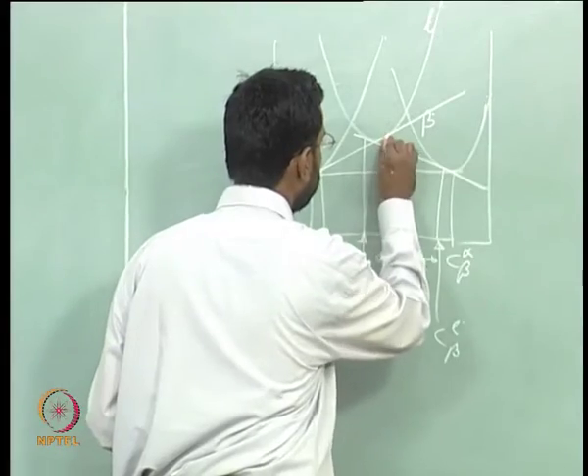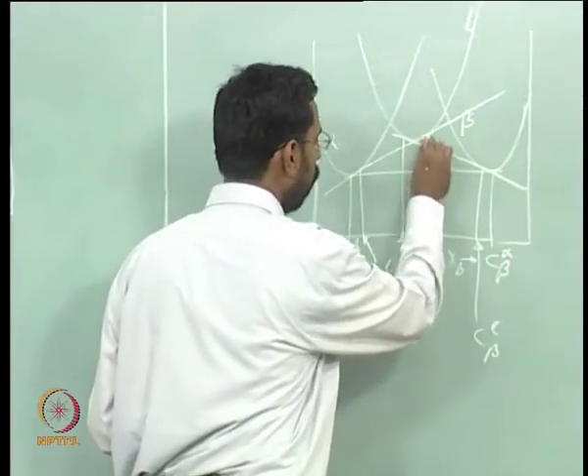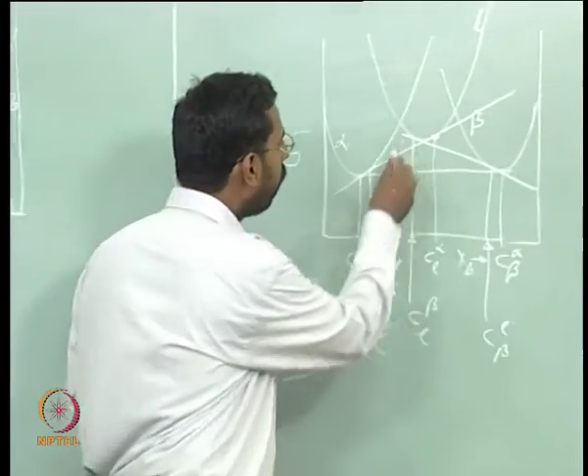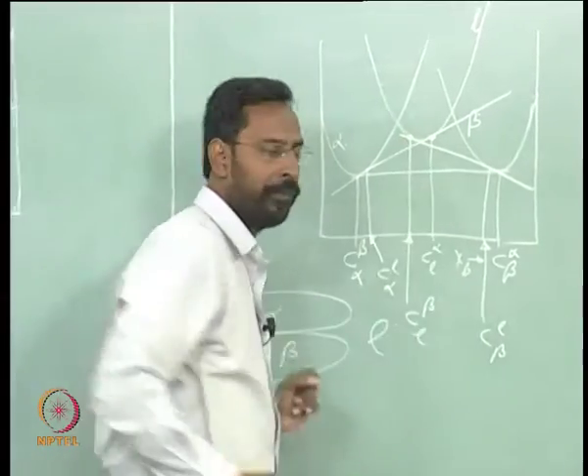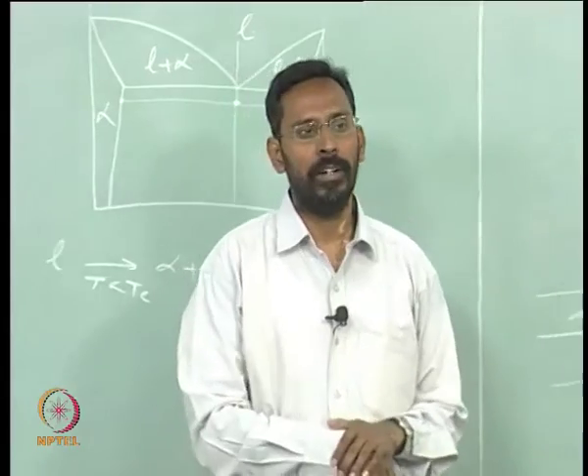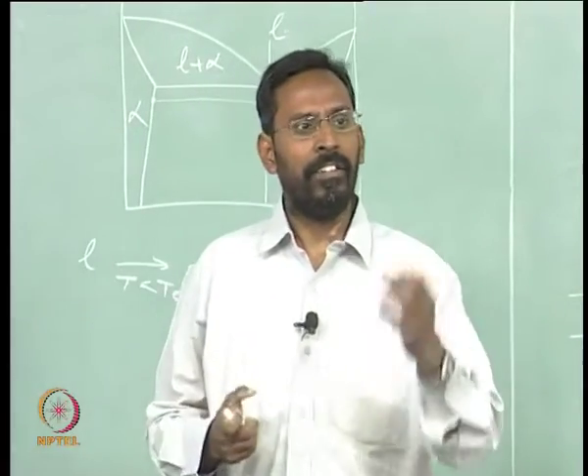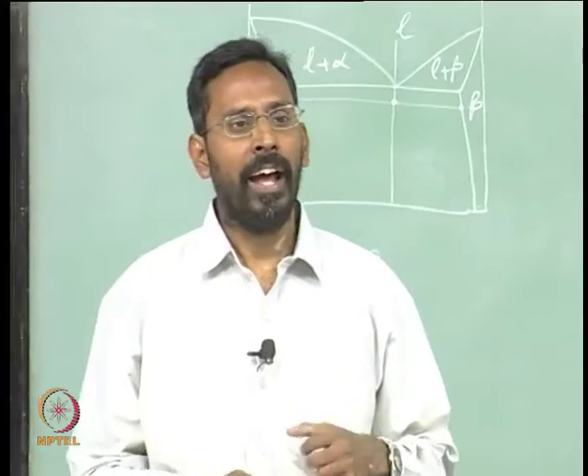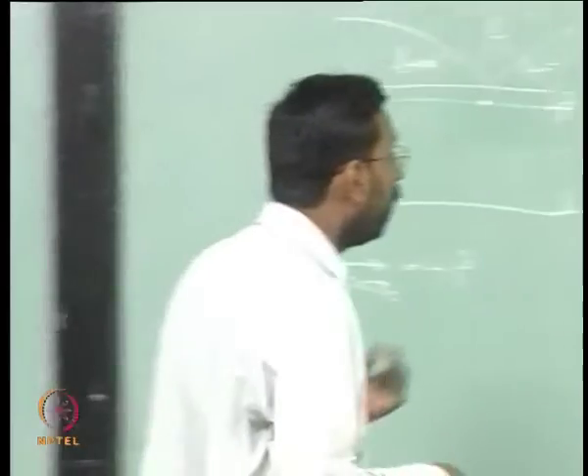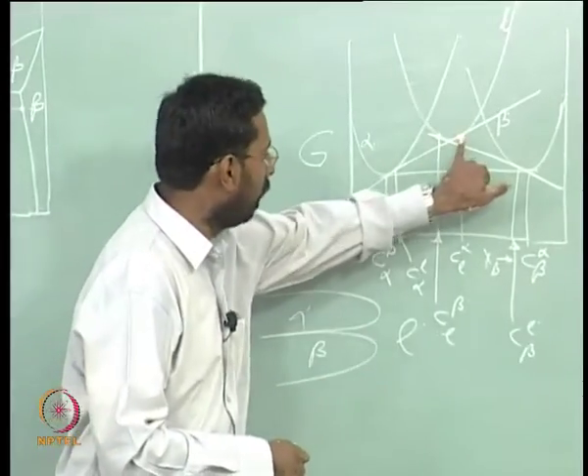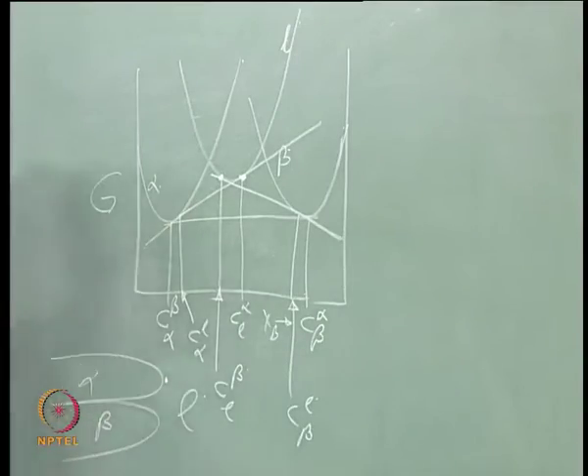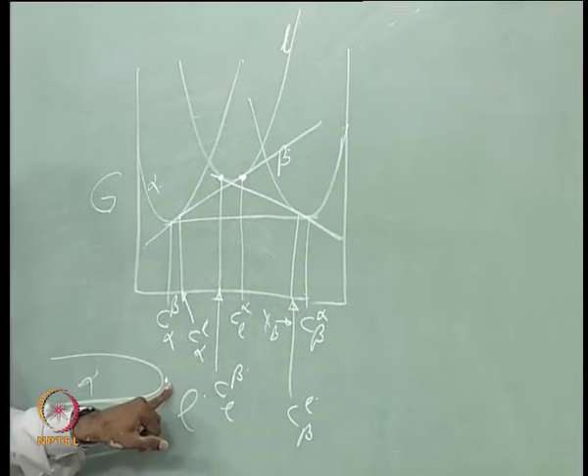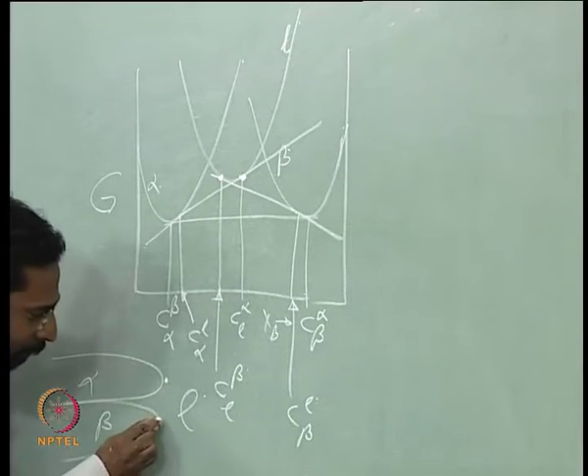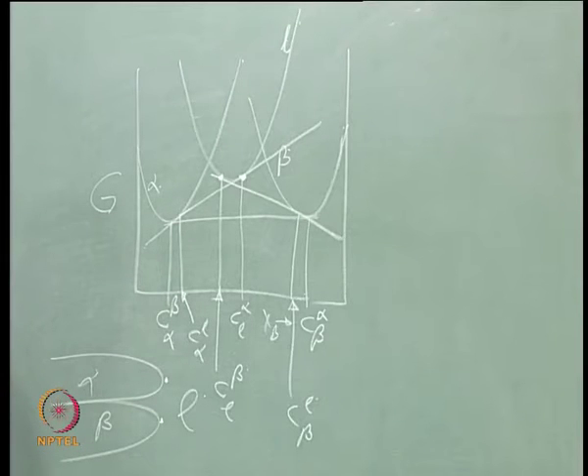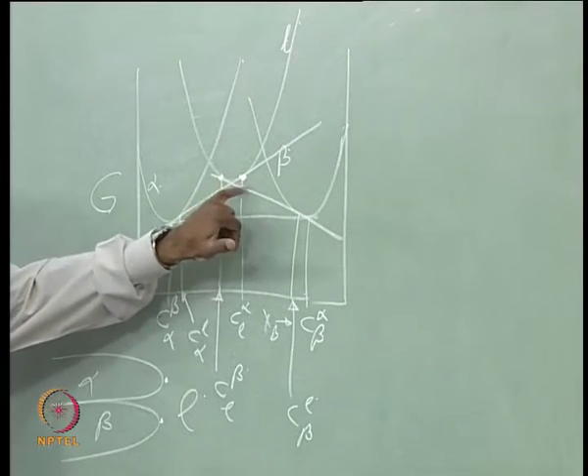It is this—this is the composition of liquid in equilibrium with alpha. This is the composition of liquid in equilibrium with beta. What does that tell you? It tells you that the liquid in equilibrium with alpha has a higher B content compared to the liquid in equilibrium with beta. That means the liquid just in front of the alpha and the liquid just in front of the beta, if I look at the compositions of those two liquids, they are not the same.